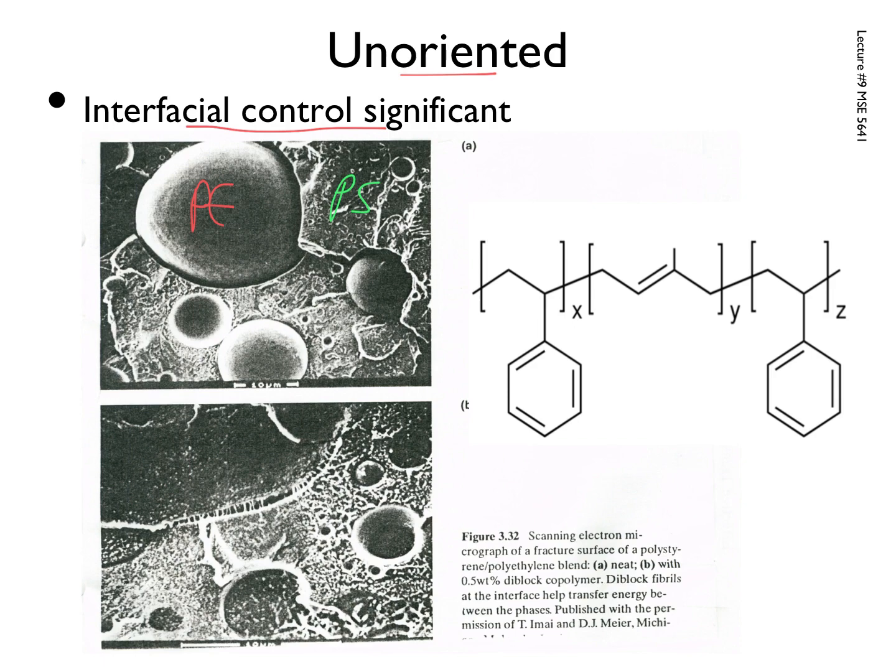And so this is a problem because you've taken that polystyrene and you've reinforced it with polyethylene particle-sized holes in the polystyrene, which is really bad for polystyrene, which is already brittle to begin with. Now you've made all these huge flaws. We know what critical flaws are, right? And how those affect properties. This is a great example. This is why we think of all plastics as Griffith solids, because they're very sensitive to flaws, like many ceramics and glasses. Similar issues, not as bad, but similar issues. And so obviously this is an example where you tried to make it better and you made it worse instead of better.